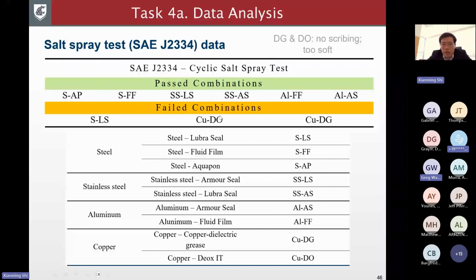For instance, the Lubra Seal on carbon steel surface. Again, Lubra Seal is a sealant, so it's not intended to be a long-lasting coating anyway. And also the DO and DG, I think, the dielectric grease and the Deox IT, are 2 lubricants. They, again, are not intended to be anti-corrosion coatings. So they didn't really pass that 5-year, or 60 cycle, test.